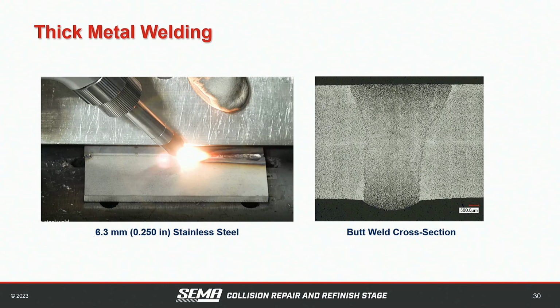So are the welds strong? This is a cross section of a 1/4-inch stainless steel. You can see on the right that the fillet is almost parallel. It's not the tornado-shaped weld that you get with TIG or MIG. You would never bevel a thicker part to weld this. You would just want to butt the parts together. And since you're focusing all that energy to the bottom, you can actually control where and what shape that weld's going to have.